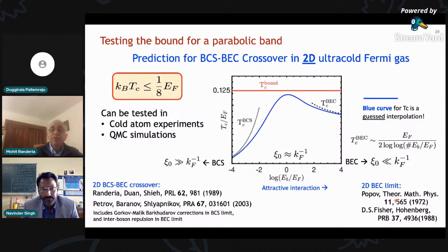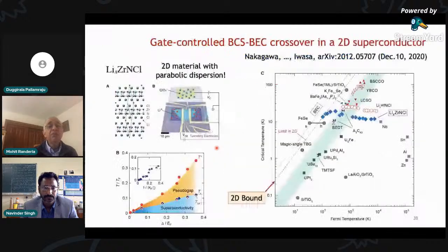But it's known from old work of Popov and Fisher and Hohenberg that the manner in which it goes down to 0 is very, very slowly. Only Russians could find a double log, right? And that's what Popov did. So actually, based on this, I've just drawn a blue interpolation, which just interpolates between these 2 limits. And we think that here, the actual answer should come close to the bound, but we have no way of knowing that it does or doesn't. It's a prediction. So we put our heads on the chopping block.